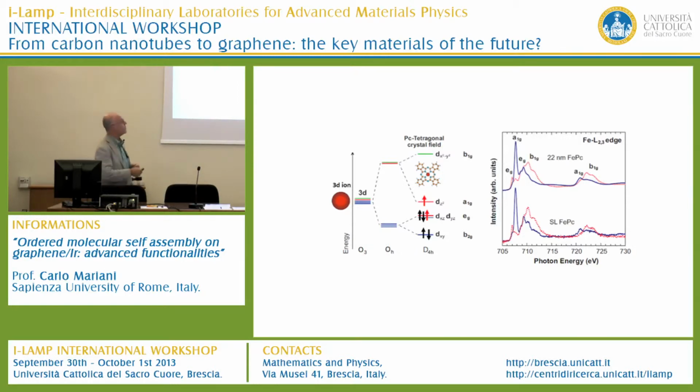On the other hand, if you look at the experimental data, this is the L23 absorption without polarization. This is just linearly polarized. Thin film, single layer: you do have mostly the same response. There is a difference, which is that the lines, the resonances, are much narrower. And narrowing may mean higher correlation.